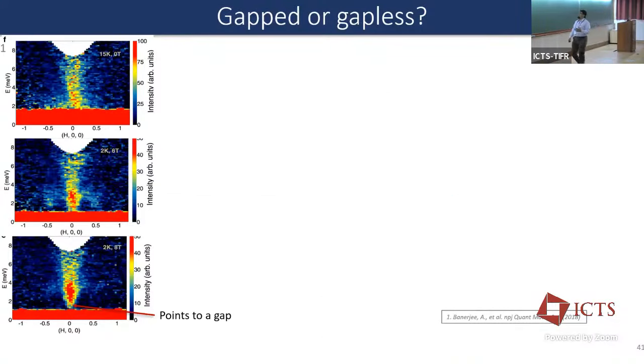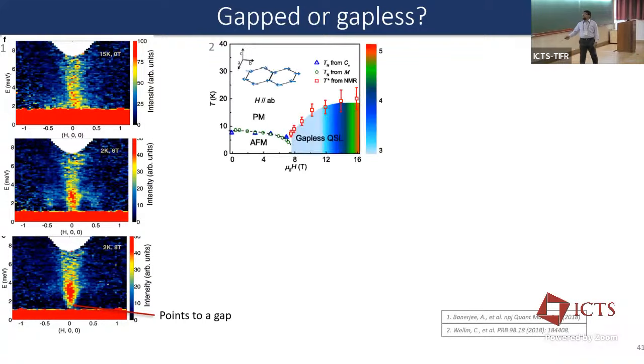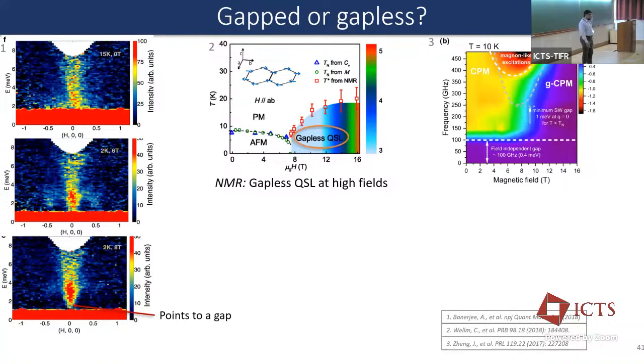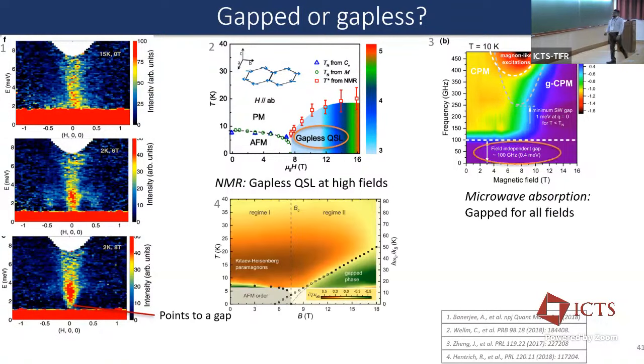So we tried to probe more whether we have gapped or gapless excitations. Now, the data that we got from HYSPEC sometime back, energy versus in-plane scattering, seems to point to a gap, but there are several other reports in literature which say this might be gapped, this might be gapless. There is a paper which came up in Chinese Physics Letters just a month ago which says that it's all gapless.